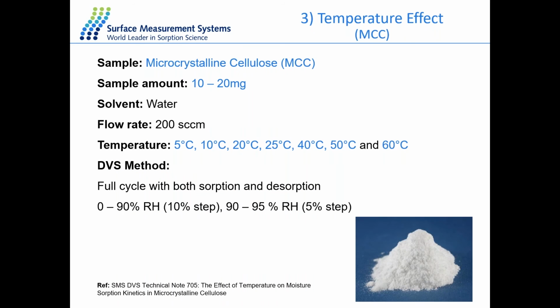So the first study is about the microcrystalline cellulose for the sorption at different temperatures from 5 to 60 degrees. We use around 10 to 20 milligram of MCC sample, and we perform exactly the same water sorption experiment from 0 to 95% RH with 10% and 5% steps.